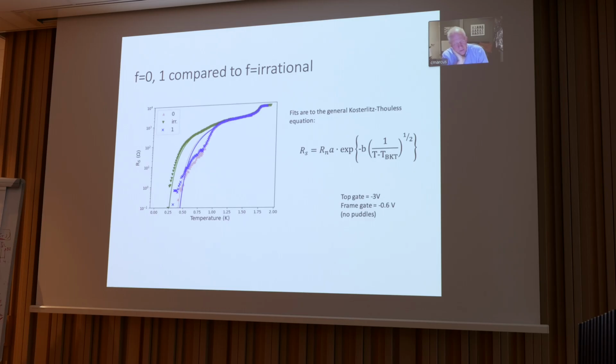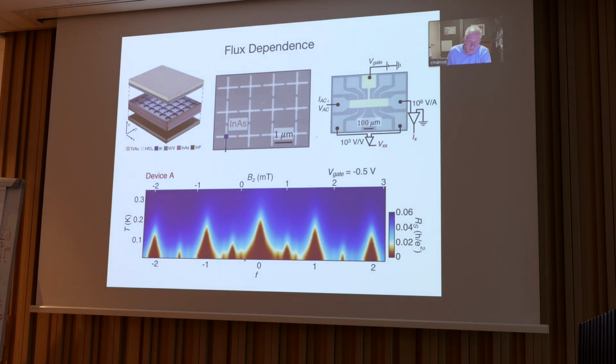What I'd like to call attention to is that I think, as everybody knows, the Kosterlitz-Thouless transition is designed to work at 0 external magnetic field, a magnetic field where the number of positive and negative vortices are equal and thermally stimulated. And in that regime, this famous Kosterlitz-Thouless form of the exponent to 1/2 is what one expects. Now, the interesting part of our observation is that we do see very nice Kosterlitz-Thouless behavior here, out in the middle of nowhere, where we take cuts at no special value at all.